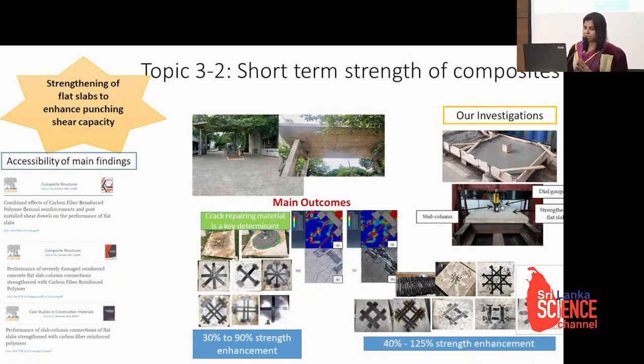I searched many possible retrofitting techniques, but I couldn't find any. Then I thought, sometimes the FRP technique will work with this one. There are many attempts done by researchers, but those didn't show a considerable strength gain. So we studied the mechanism, that means the interface mechanism, between the column and the slab. And we developed a number of configurations to see whether they work to enhance punching shear capacity of flat slabs. We noticed we can achieve 40% to 125% punching shear strength gain with the selected configurations.